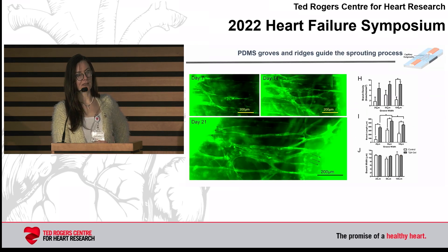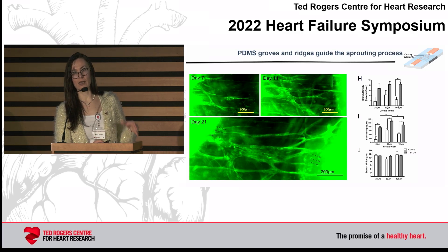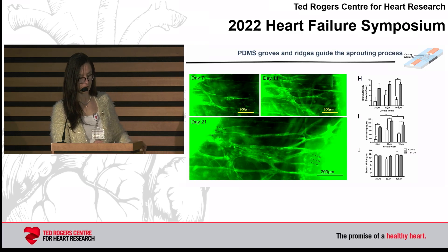This is what the blood vessels look like — explants from GFP-positive mice under control of actin promoters. You can see that after about three weeks you get microvasculature connecting. There was definitely an impact of the topographical cues on the types of branching of the vessels, and we saw optimum vessel length and branching with about 50 micron cues.